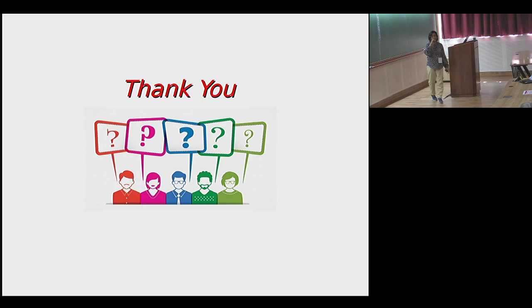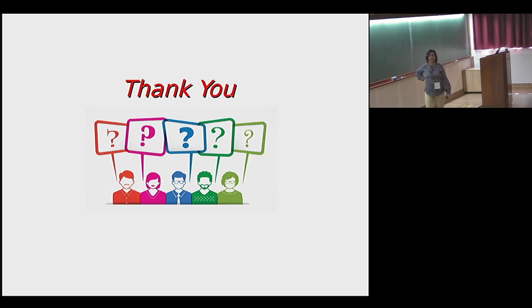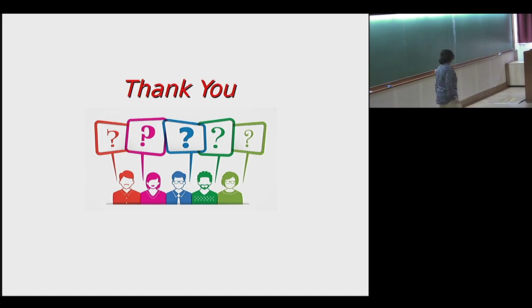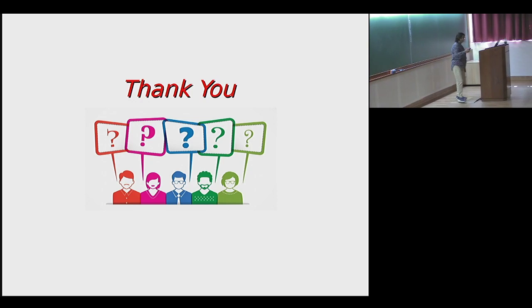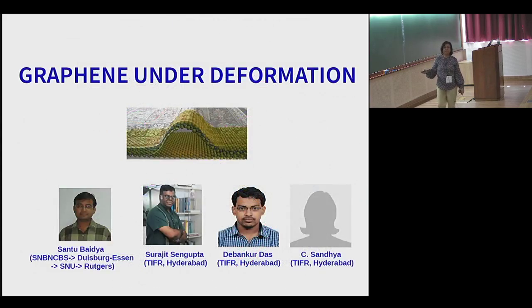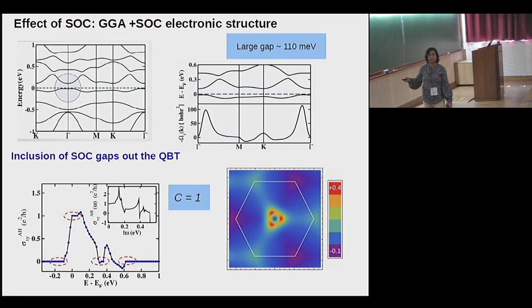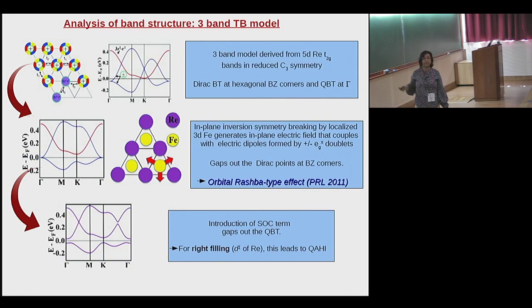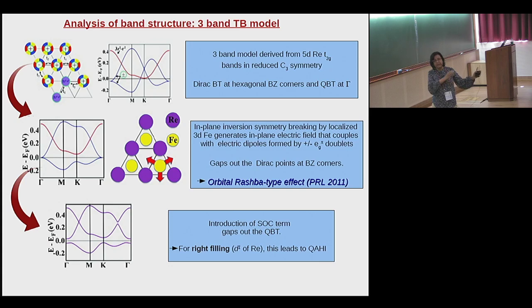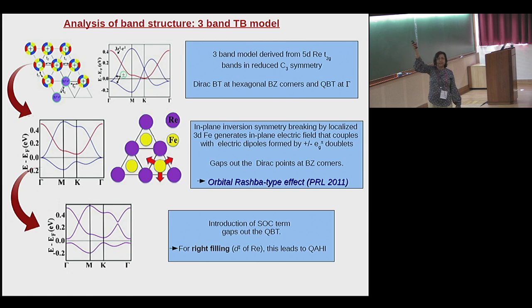Questions? Yeah, sure. You want the band structure with the substrate geometry? The last slide of that. This one? Where you showed the spin-orbit coupling band structure, the 3-band model. Yes, I think you are referring to this one. So this is also a ferromagnet. In the ferromagnetic state, you should also see the spin splitting. These are the 3 bands which are in one of the spin channels, because you have a very large spin splitting, since it's a half metal. So the other spin channel is completely insulating to start with, without spin orbit, without anything. There is a very large spin splitting because of the spin splitting of the iron. So this is basically the 3 bands in only one of the spin channels.